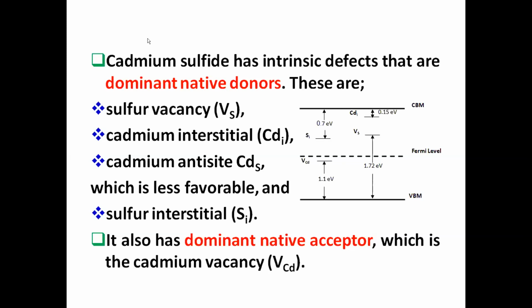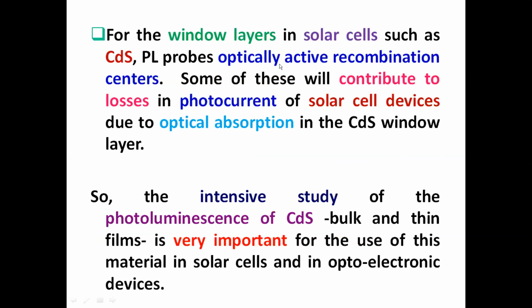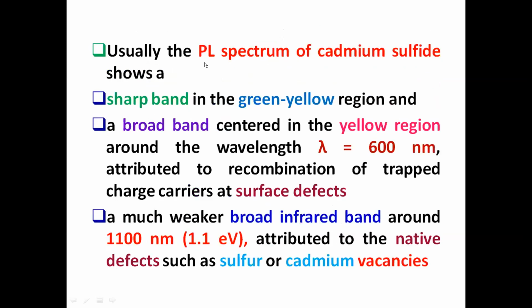For the use as window layer in solar cells such as CdS, PL probes optically active recombination centers. Some of these recombination centers contribute to losses in photocurrent of solar cell devices due to optical absorption in the CdS window layer. So the intensive study of the photoluminescence of cadmium sulfide as bulk or thin films is very important for the use in solar cells. Usually, the PL spectrum of cadmium sulfide shows three peaks.